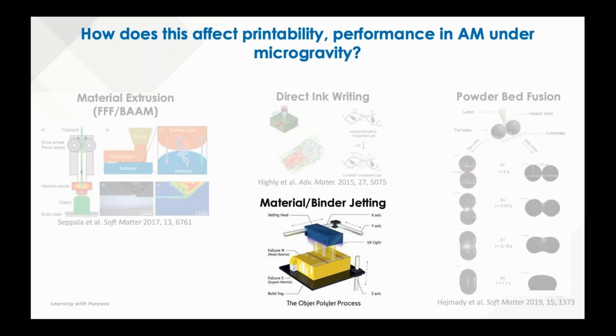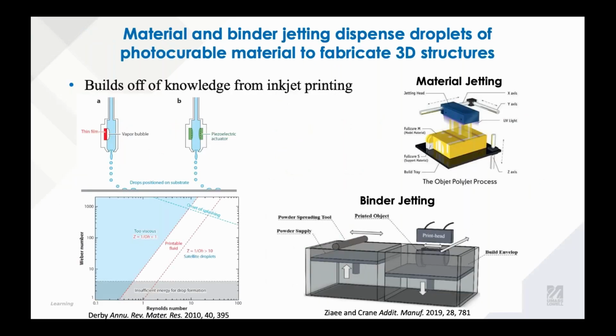All right, and then the third example here would be material or binder jetting. So next slide. And so here we've got material jetting and binder jetting, and in both of the cases there is a material that's being jetted. In the material jetting example, the material that's being jetted is the material that you want to be printing with, and then often it's UV cured, and then sometimes there's a support material as well. In binder jetting, the material that is being jetted is going to be printed into a powder bed, and so that means that with binder jetting we can start to get at printing of green parts for metal or ceramic additive manufacturing.